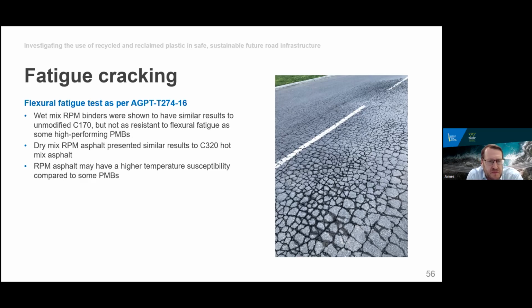Recycled plastic modified asphalt produced through the dry method again presented similar test results to unmodified C320 hot mix asphalt, as might well be expected, given that the recycled plastic incorporated through this method isn't expected to modify the binder properties. There was a suggestion in the data that potentially the recycled plastic modified asphalt might have a higher temperature susceptibility compared to some of the premium polymer modified binder asphalts. Next slide, please.